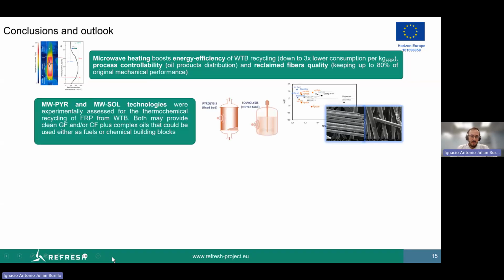So, conclusions and outlook. The microwave heating boosts the energy efficiency of wind turbine blades recycling down to 3 times lower consumption per kilogram of FRP treated. It enhances also process controllability, oil products distribution, and also the reclaimed fibers quality, keeping up to 80% of the original mechanical performance. Both pyrolysis and solvolysis technologies were experimentally assessed. Both may provide fibers and oils.